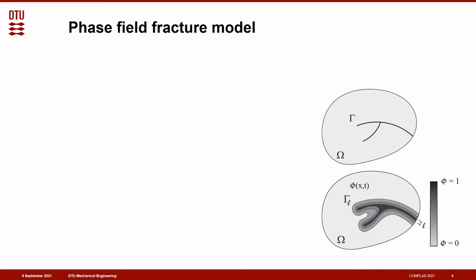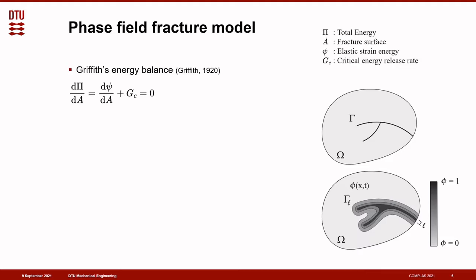For example, the phase field can take the value of 1 in the crack phase and the value of 0 in the undamaged material points, varying smoothly in between. One of the beauties of this method is that it provides a computational framework for the Griffith's energy balance. As you know, Griffith, one of the fathers of fracture mechanics, postulated that a crack will grow if the energy released by the solid reaches a critical value, the so-called critical energy release rate, or basically the material toughness.